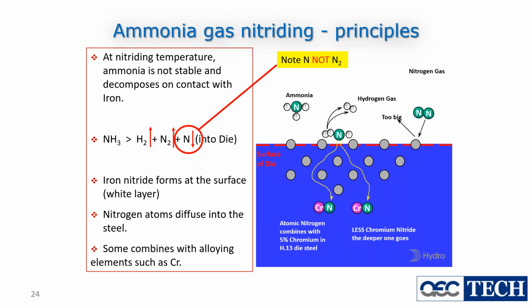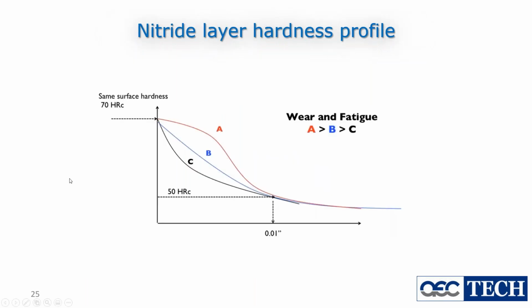Now, like all things in material science and metallurgy, there's a phase diagram for nitrogen in steel, and it makes different phases. Yaya's going to cover that technically a bit for you in a minute. But this nitrogen diffuses into the surface. Now, we're looking here at three different profiles of hardness we could get. This is the edge of the steel. This is the depth going in. When we do the first nitriding, we tend to get a curve like C. Good hardness on the surface, but it's not really got any depth behind it. I believe that's how people describe the Detroit Lions running backs.